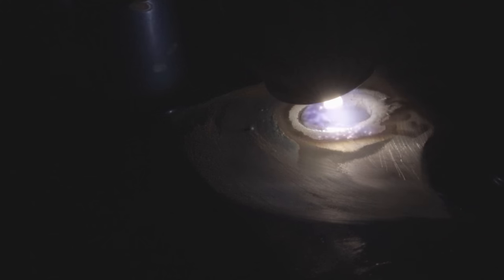If you don't have enough torch time pushing all the junk out, you're going to end up with constant pinholes and a lot of issues like particles floating in your pool, porosity, etc. So make sure you take your time and don't add the filler until all the junk is displaced and the bubbles are gone.